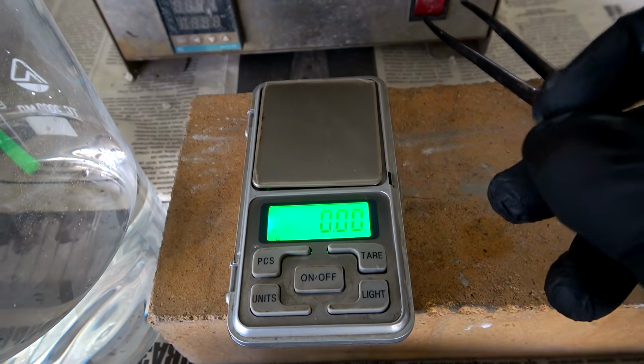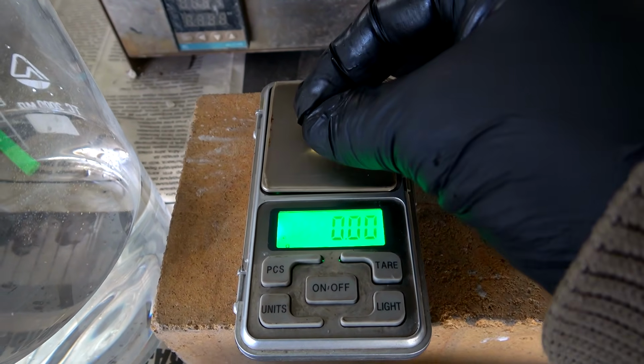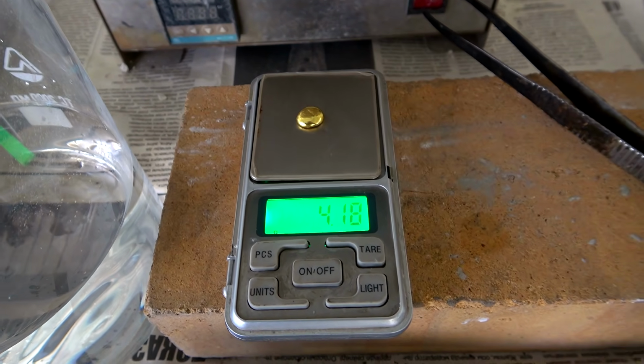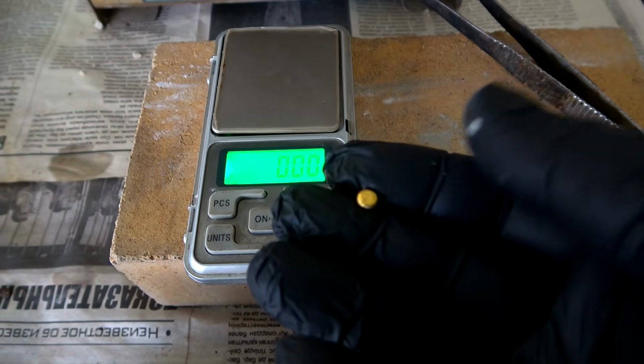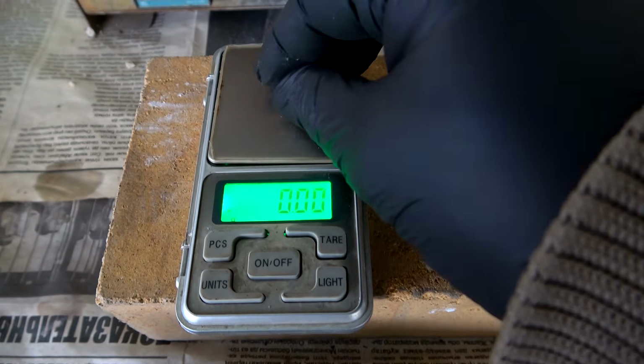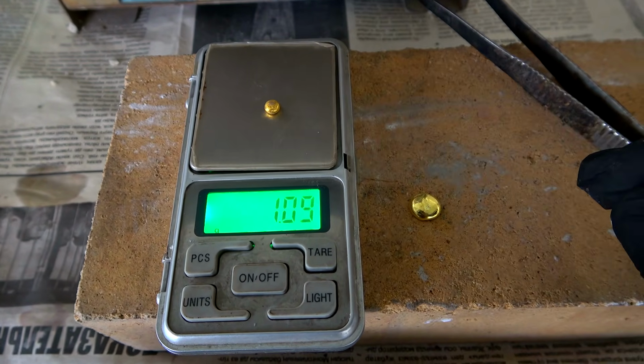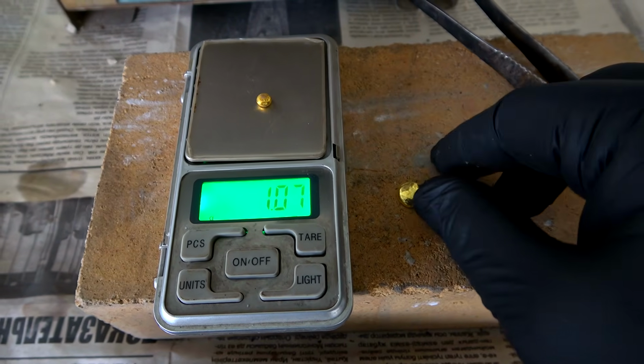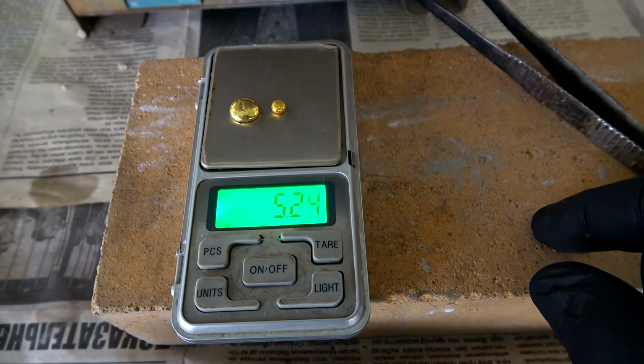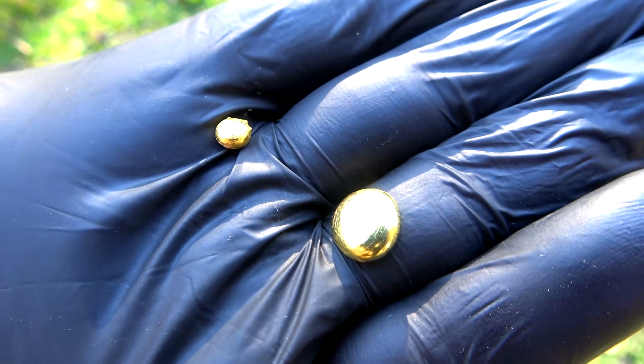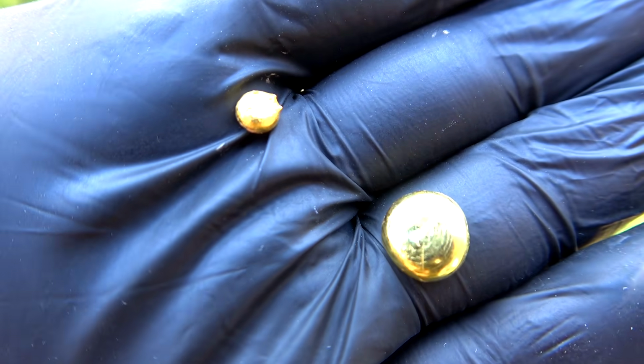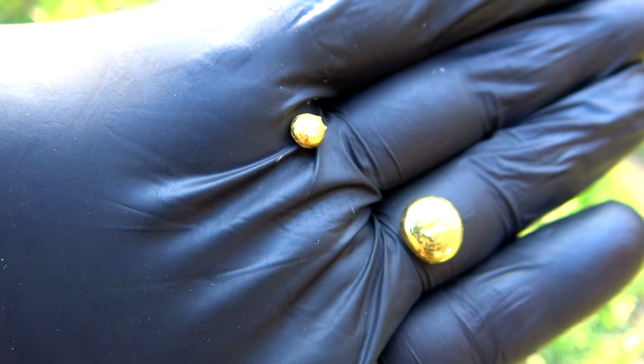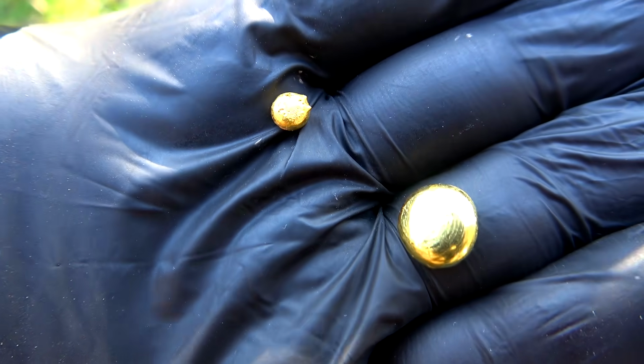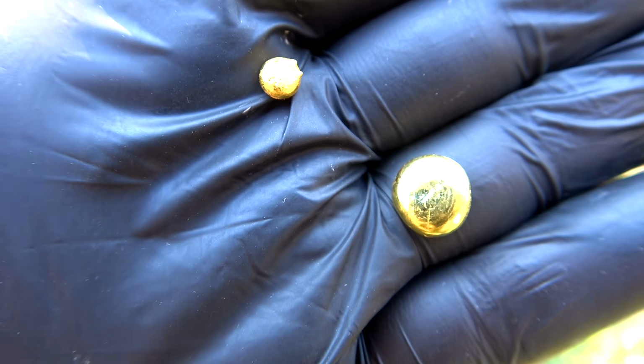4.18 grams of 800-grade gold dust was contained in the concentrate after enrichment. I also obtained 1.09 grams of pure gold using a prospecting pan and chemicals. Now you can compare the results. This type of gold is usually elusive using simple means, and chemicals aren't 100% effective at extracting it. Using flotation, I spent pennies on diesel fuel and a little lead, but using chemicals, the same procedure would have been expensive, time-consuming, and resulted in significant losses of precious metal.